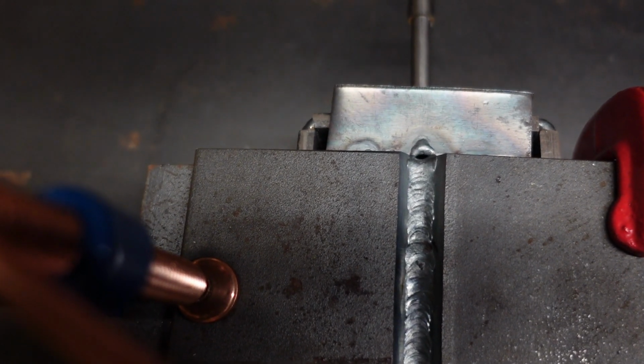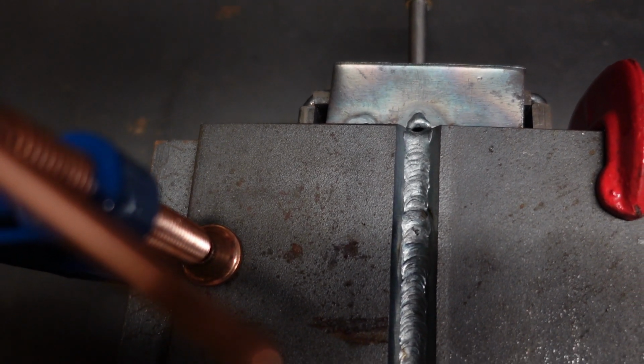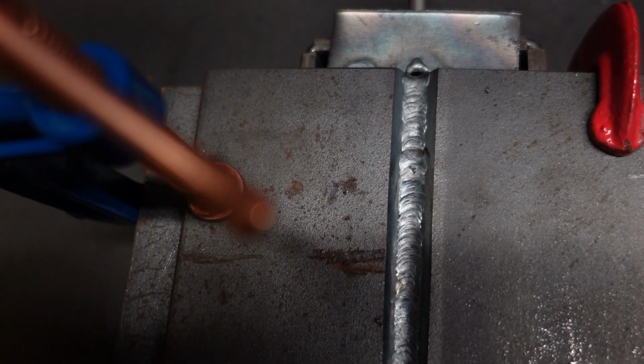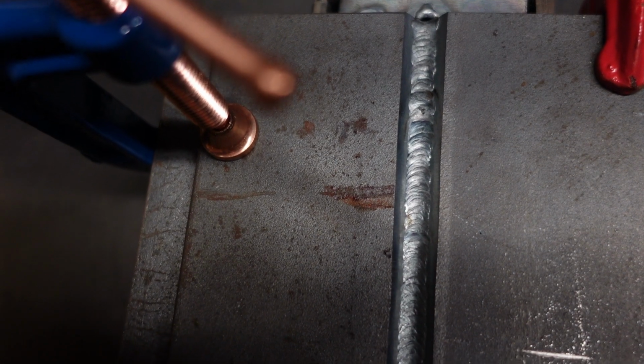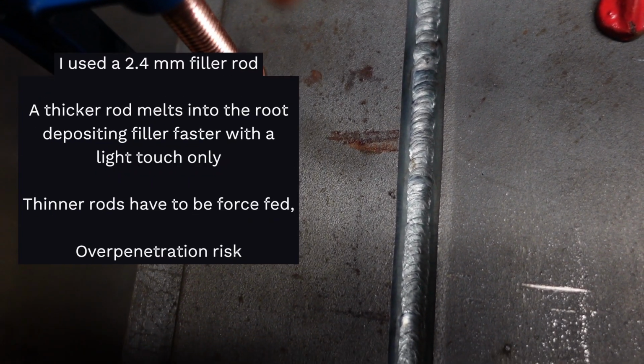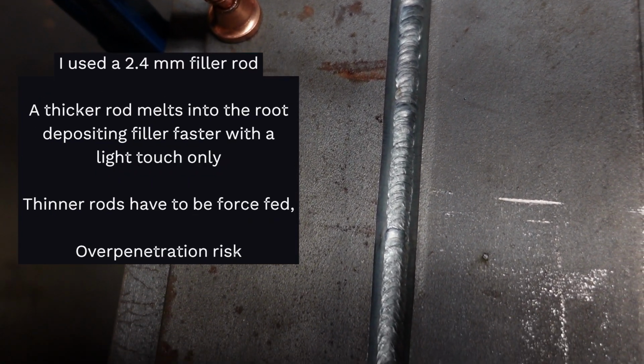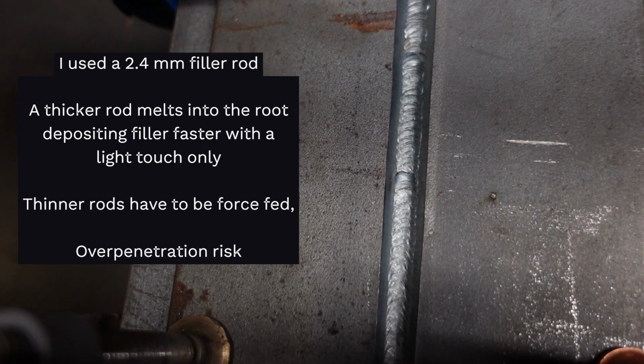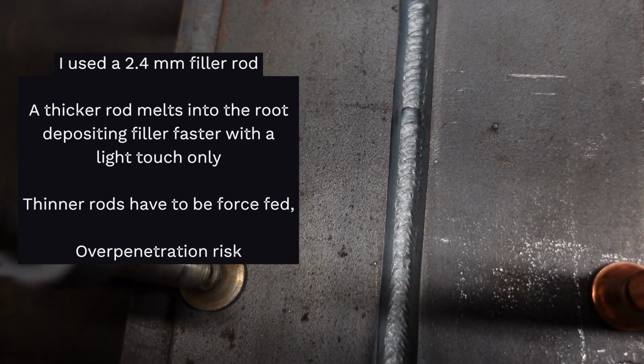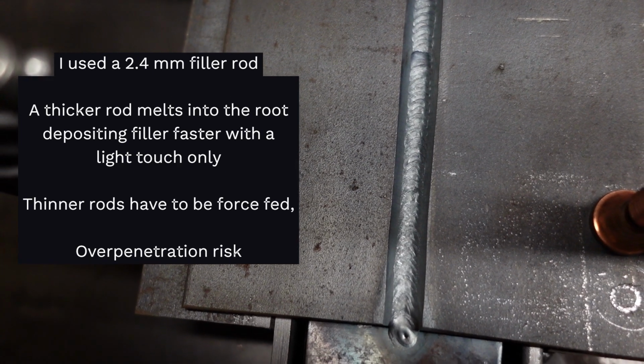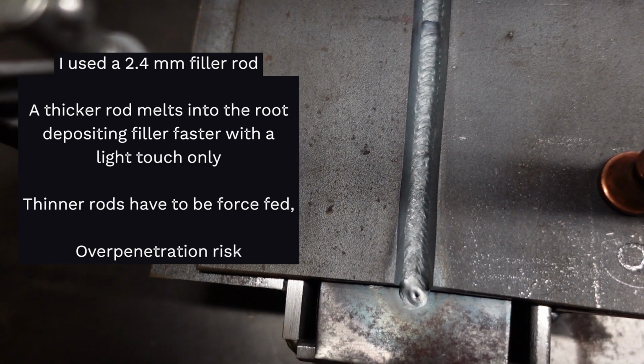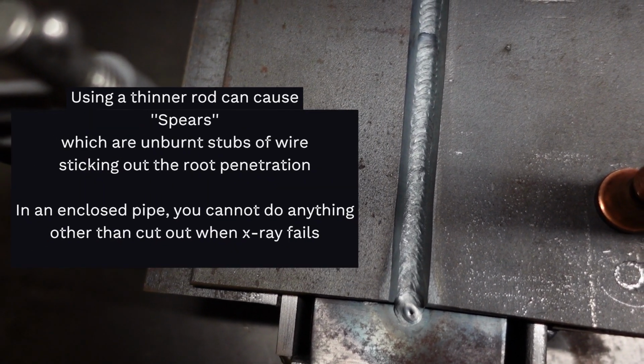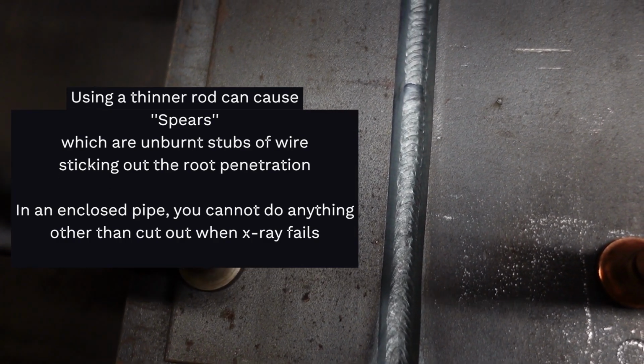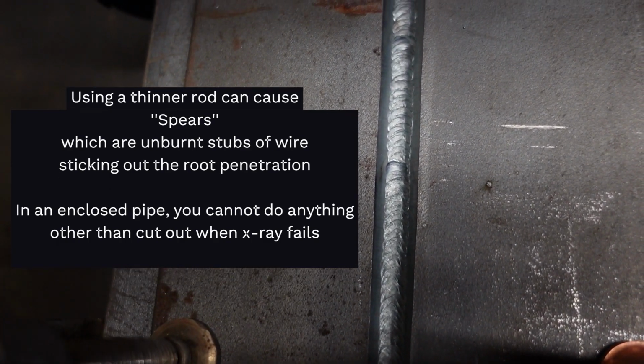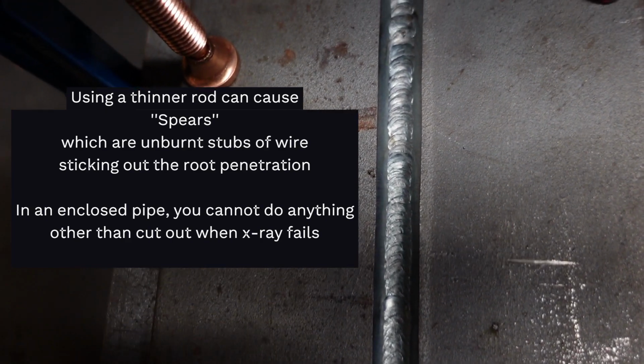This is the finished root. Unfortunately, I did not set my camera to record after I got the close-ups through a mask lens. You can see the root is right down the prep where you would focus on the root edges and get that penetration. I use a 2.4mm filler rod when rooting, as it deposits filler faster and melts into the weld pool with just a touch, whereas with thinner rods you have to feed in, which can slow your travel speed, causing your roots to sag and over-penetrate.